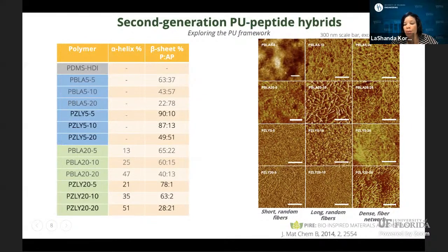So here we can see a couple of things that are happening. For both PBLA at the 5% composition, so whether you have a block length of 5 or 20, but a composition of 5% of the peptide in the non-chain extended PE, you can see short and random fibers. As you increase the peptide content, you then move to more long range but random fibers. And then at the highest composition, which is 20%, you see a denser fiber network. And we believe this will have impact, of course, on the overall mechanical properties of the system.